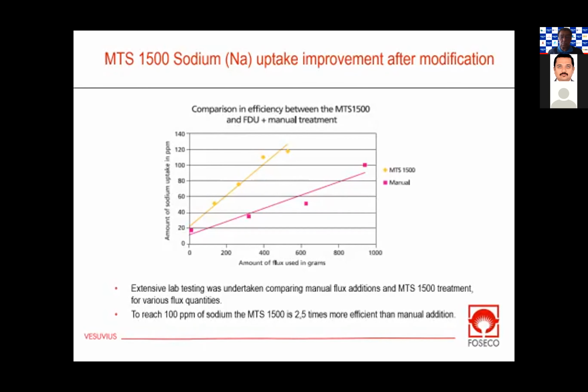And what you can see is that if you use this MTS process, basically the sodium pickup for the same parameters, the same crucible, the same condition, the same alloy, everything else being the same, the sodium pickup is about 2 to 3 times higher when we use this MTS process than when people use the traditional method of introducing sodium.